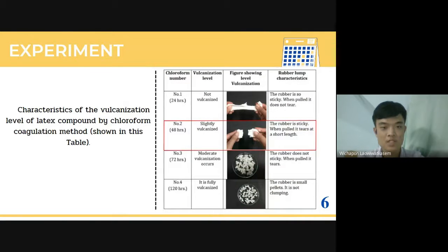Now, I'm going to talk about the experiment characterizing the vulcanization level of latex compound by the chloroform coagulation method. The results show that number 1, 24 hours, is not vulcanized. The rubber is so sticky when pulled that it does not tear. Number 2, 48 hours, is slightly vulcanized. The rubber is sticky when pulled, and it tears at a short range. Number 3, 72 hours, is moderately vulcanized. The rubber is not sticky when pulled, and it tears. Number 4, 120 hours, is fully vulcanized. The rubber is more pellet-like and is not clumping. The most suitable latex for an athletic arm sleeve is number 2, 48 hours, because of its ability and properties.